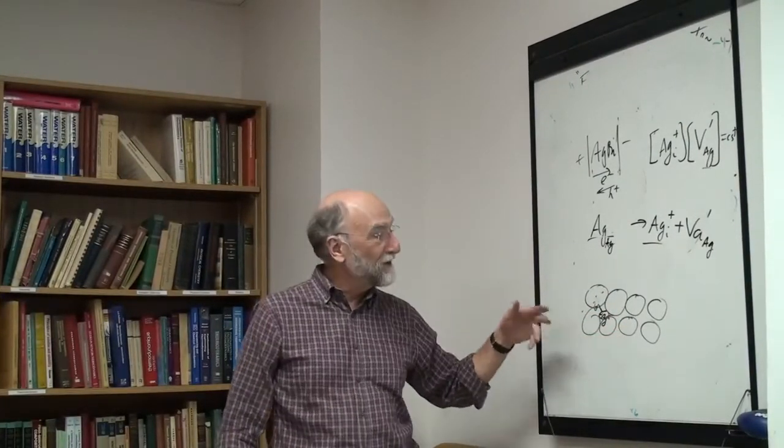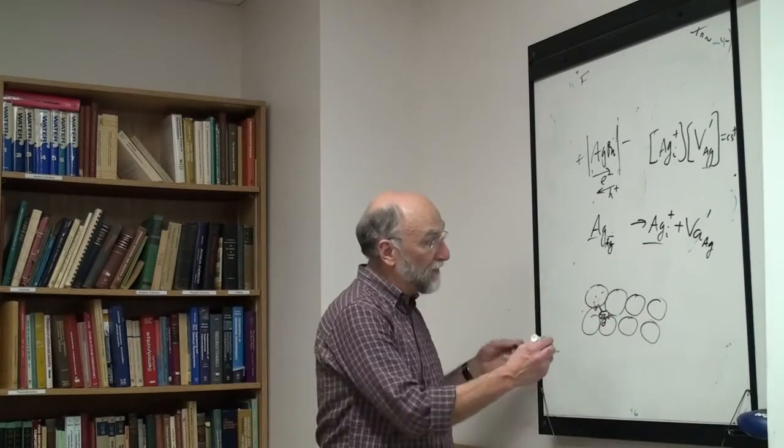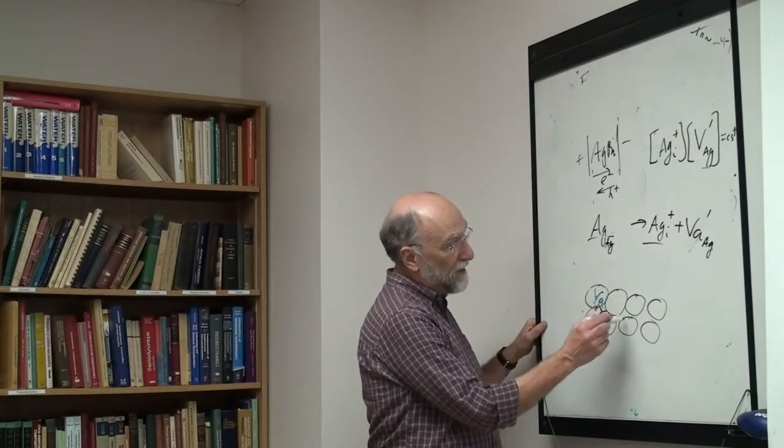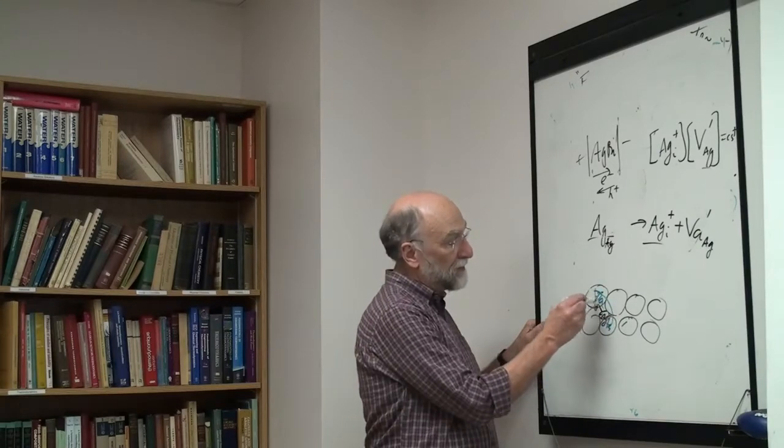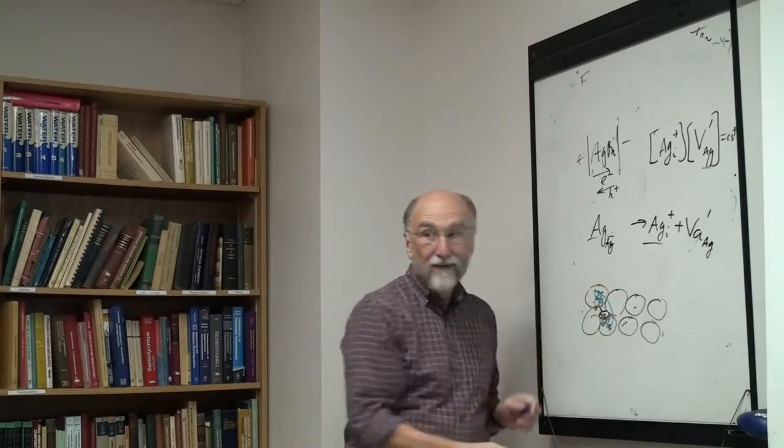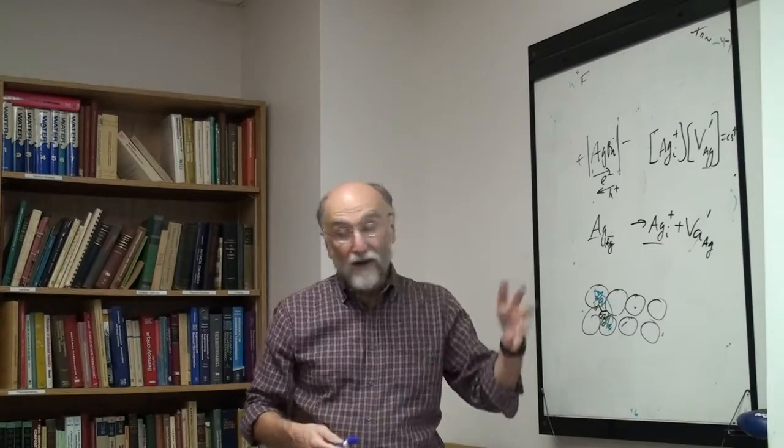This is ionic conduction. The silver ion is an ionic conductor. The silver ions move, not as electrons, they hop as ions, positive ions. The vacancies also have a hopping mechanism. You have a vacancy here, the silver is next to it, the silver hops into the vacancy, now the vacancy is here. So it's definitely an ionic conduction.